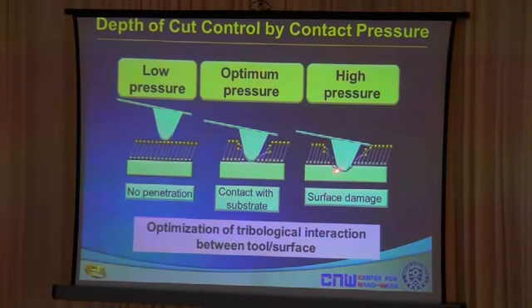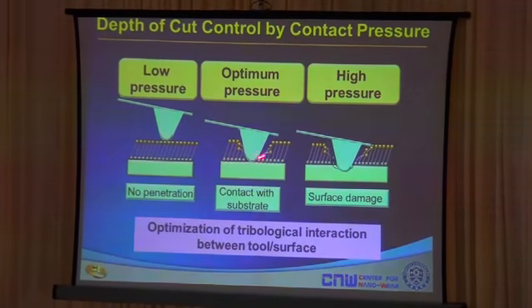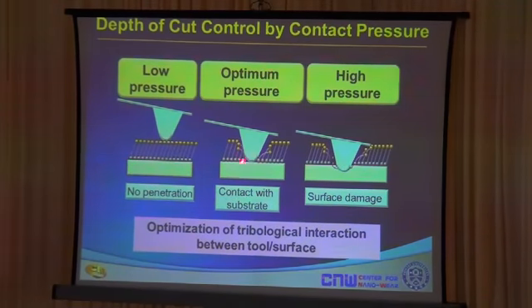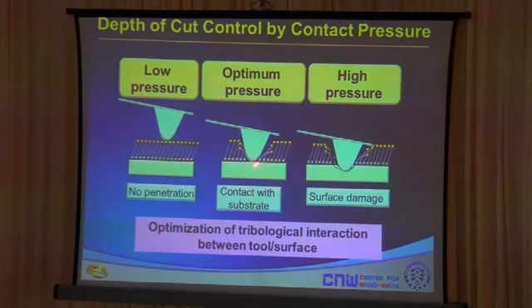If we have too low contact pressure, you will not be able to penetrate the organic film. If you have too high contact pressure, you go beyond the organic film and you start destroying the substrate, which is not what you want to do. Basically, you want to optimize the contact pressure so that you are able to just remove the self-assembled monolayer as shown in this particular figure. Obviously, this needs a lot of optimization, modeling, and also trial and error. And in the end, we're able to achieve this, and we're able to remove just the top layer. And these are the patterns that we're able to achieve with this technology.